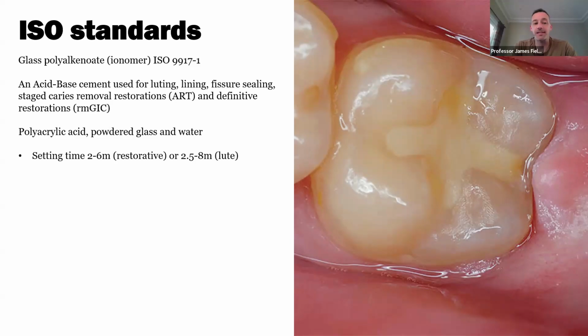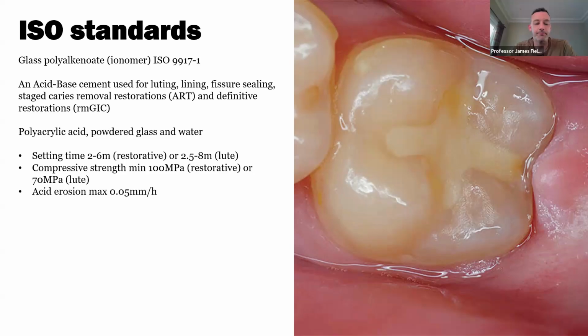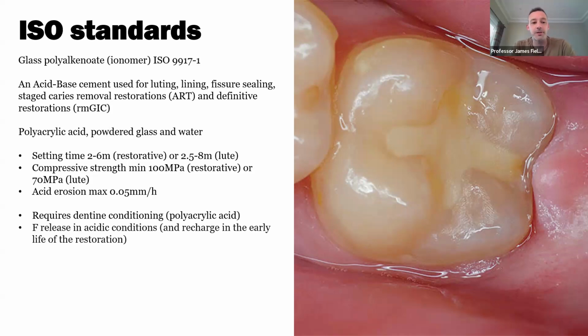So the ISO standard stipulates how long these have to set by, if they're used as restorative materials or lutes, and how strong they can be, again, if they're used as restorative materials or lutes. And interestingly, a lot of people forget this, but when we're using glass ionomers, we should condition the dentine with a polyacrylic acid. If we're using phosphoric acid, it's often too aggressive for dentine, and it's often assumed that we don't really need to condition the dentine at all, but you will get the best result by using a relatively mild acid like polyacrylic acid on dentine before applying a glass ionomer.